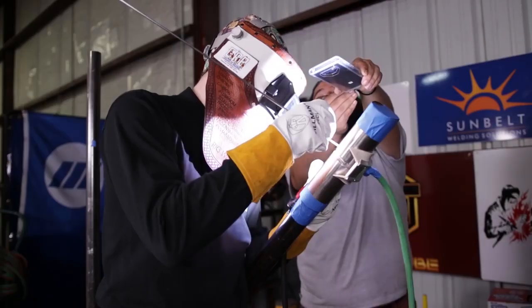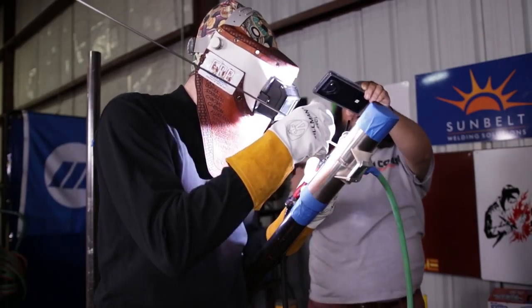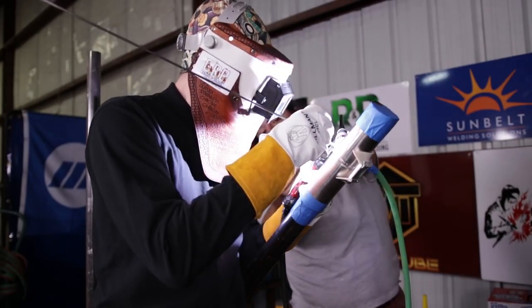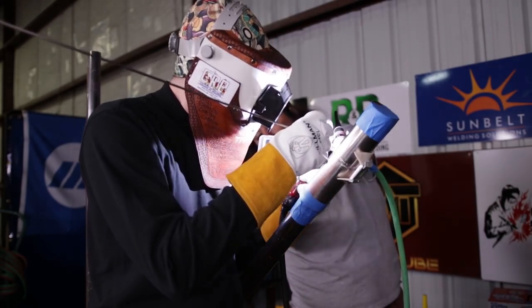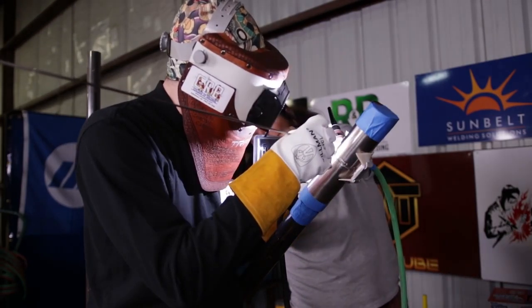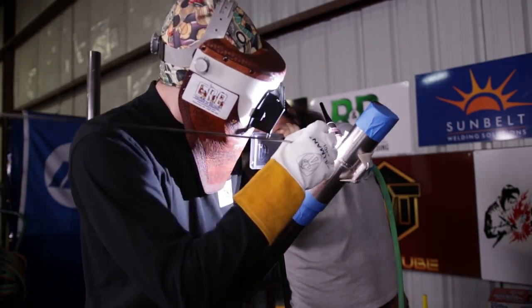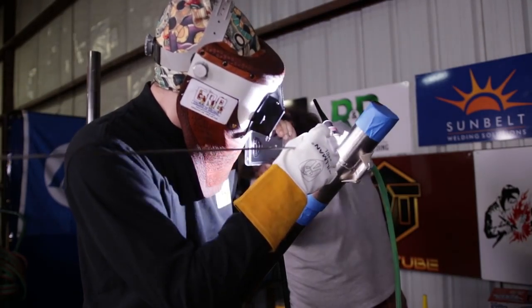But essentially, if I'm welding that particular technique, then what I'll do is I'll create a welding current. I'll create a weld ripple, and then I'll drop the current and protect that deposit metal away from the atmosphere. But how long the deposit metal is protected away from the atmosphere depends on how much energy I expel to make a particular ripple. If the ripples are very light, if little energy was used to create a ripple, then I can get away with maybe 4 seconds. If it's a lot of energy expelled, I can have them shield it for 6 seconds, 8 seconds.